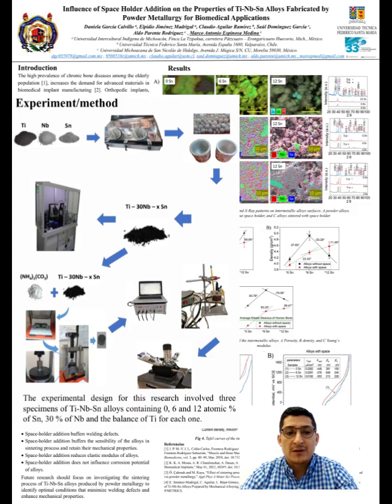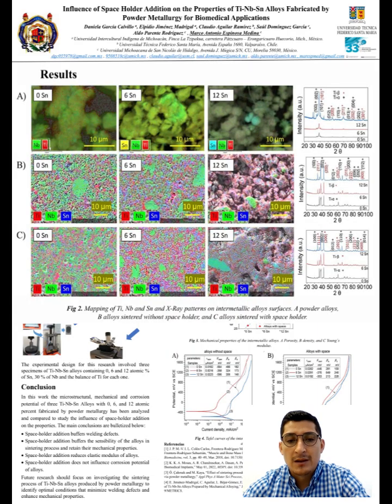The experimental design for this research involved three specimens of titanium, niobium, and tin alloys containing 0, 6, and 12 atomic percent of tin, 30% of niobium, and the balance of titanium for each one. The results of the experiment are presented in the following figures.